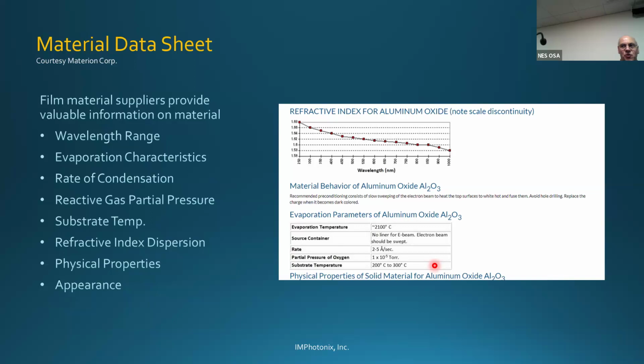There are ways of measuring absorption, but with oxides and these interference coatings, the materials that we select are specifically for low absorption. Now, with physical vapor deposition, you are going to get some absorption no matter what you do with your partial pressures and trying to get the right stoichiometric properties. So in the industry, we have to post-bake the coatings for some of these oxides in order to basically re-energize the coating and re-oxidize it to lower the absorption.